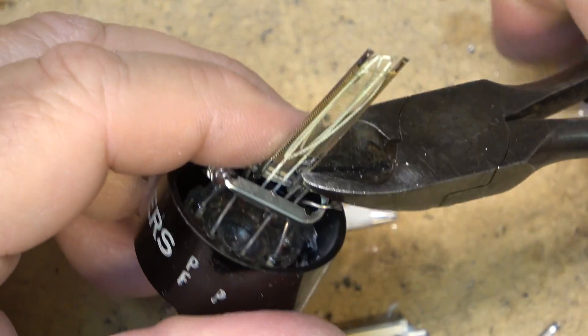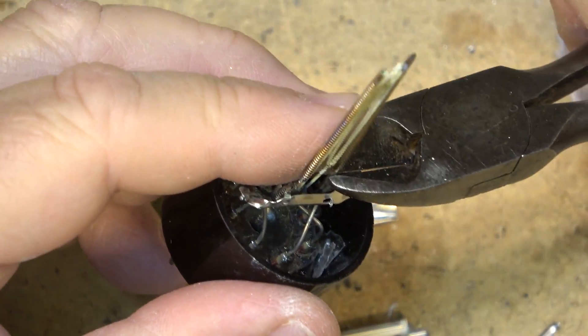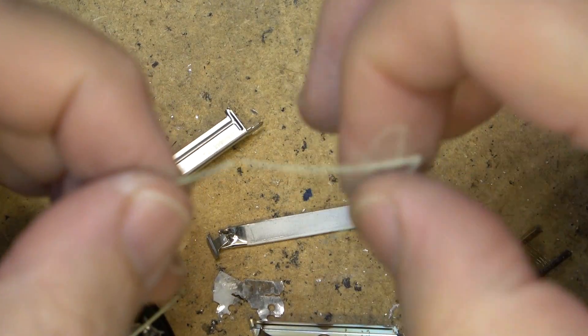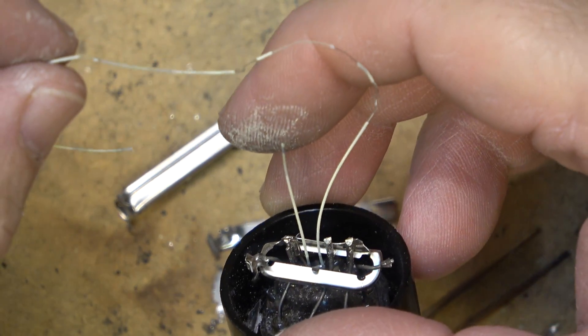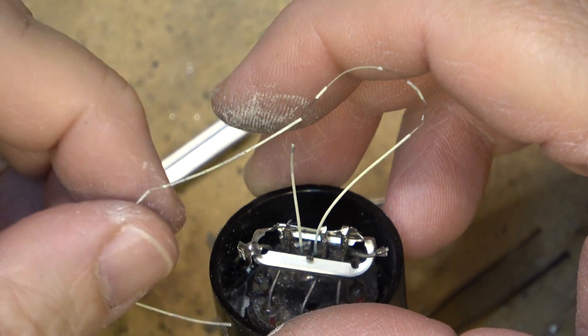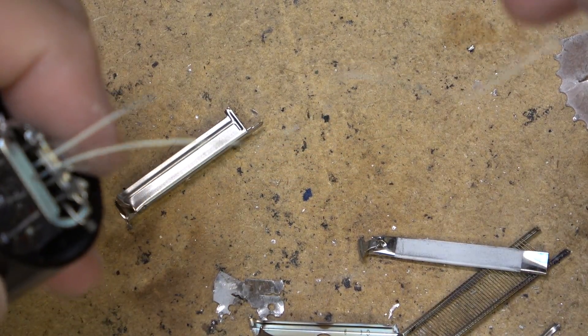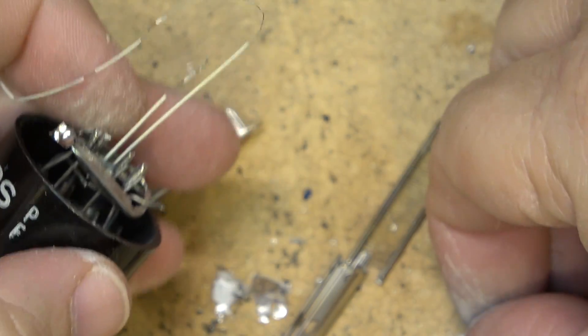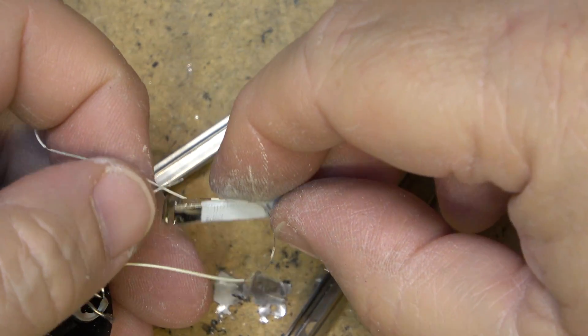If I cut off this one, we can remove the screen from the filament. The filament was just a piece of tungsten wire with a coating on it. This is an insulation. That's why this didn't burn up right away. It actually broke where there was none of this insulation. This keeps the air away from it. The reason this coating is there is to prevent a short to the cathode. They coat the filament wire, which is a piece of tungsten, and put that inside to heat the cathode. This is what happens when you get what is called a heater to cathode short. This coating breaks down and causes the heater to short to cathode.